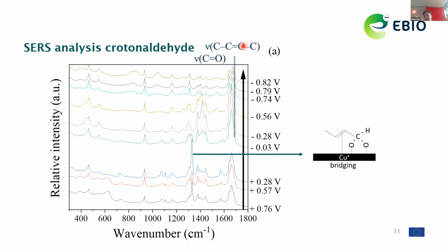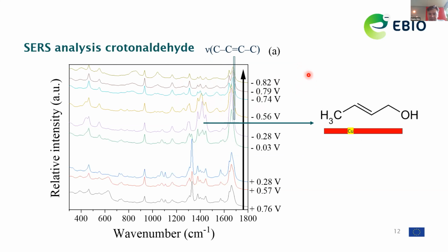Remember that the selectivity to the alcohol, so the crotyl alcohol still containing the C=C in the molecule, remains rather high, above 70% if we start from half a molar. And also the product, these peaks that you see also at negative potentials, are now indicative of some adsorbed product, the alcohol, also in higher quantities than we observed for the butyraldehyde to the butyl alcohol. Okay, yes, and that's shown here, what I explained already.